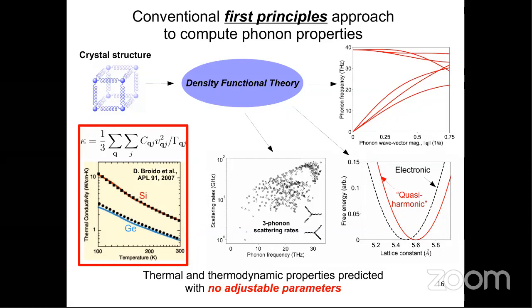So conventionally, in these first principles approaches, people who have done these calculations typically restrict the calculation of free energy, that is the vibrational component of the free energy, to the harmonic term, and that's why the name quasi-harmonic. And also the thermal conductivity calculations are typically restricted to the case of interactions among 3 phonons only. So for the purpose of this talk, I will label this approach of using quasi-harmonic phonons and 3 phonon scattering processes as the conventional approach.